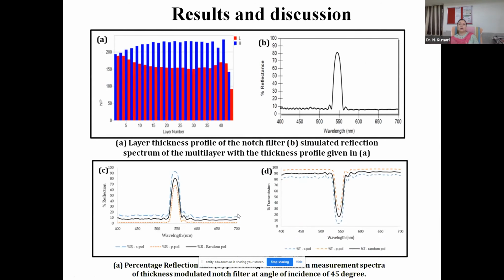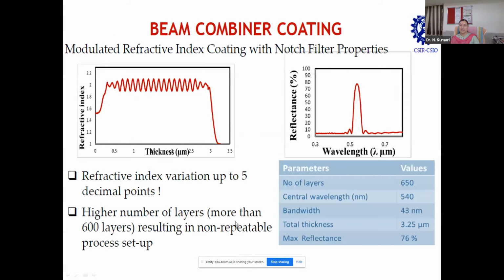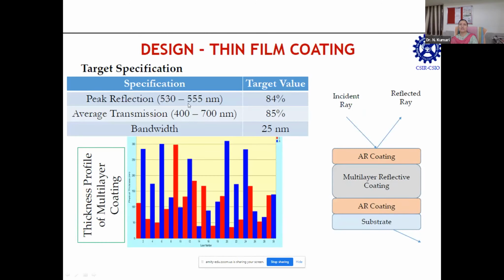So depending upon these kind of design structures, we have fabricated different kinds of filters for avionics applications, and also after optimizing these processes, we developed a beam combiner coating. Depending upon the optimization of this filter, we did some computational optimization for this, and then we did the fabrication using these parameters. So we have modulated the thickness in such a way that the refractive index gets modulated, because the two are related when we talk about the multi-layer structure.